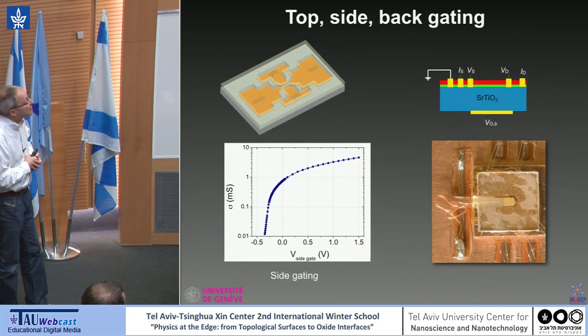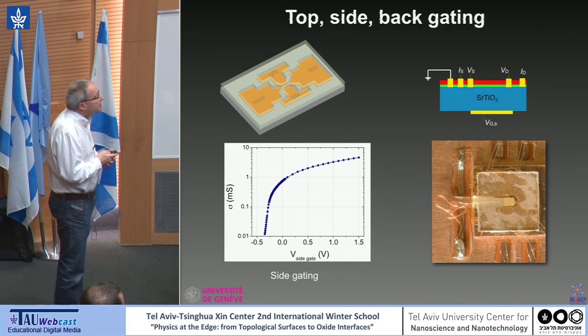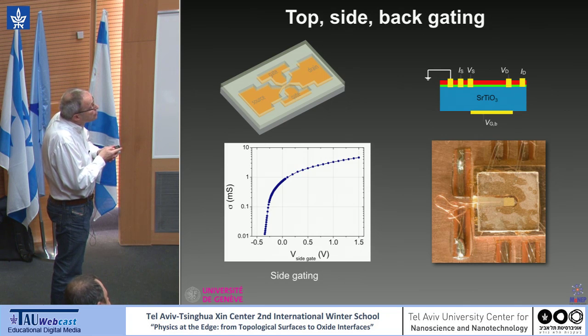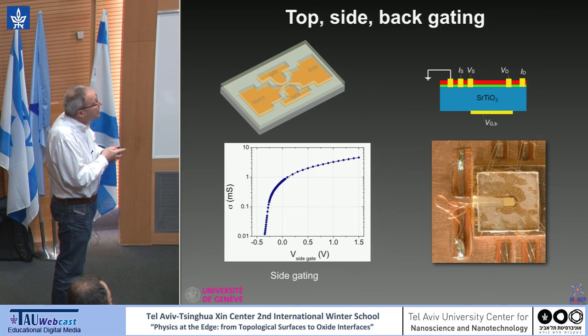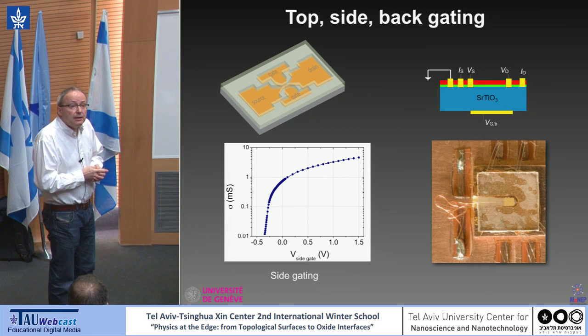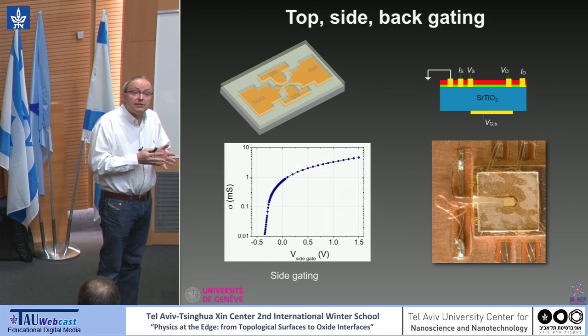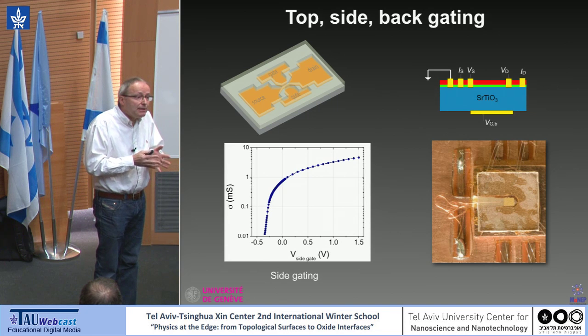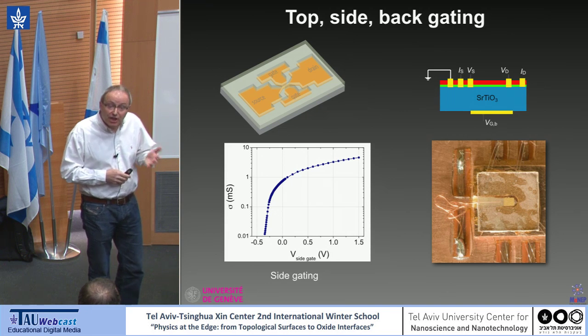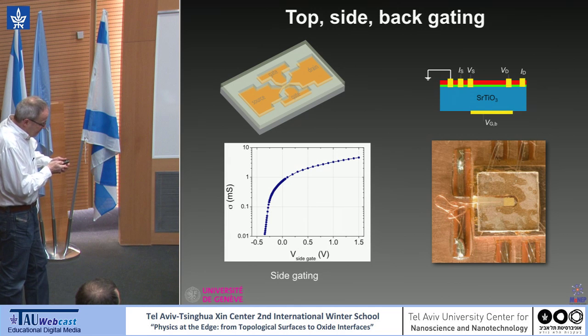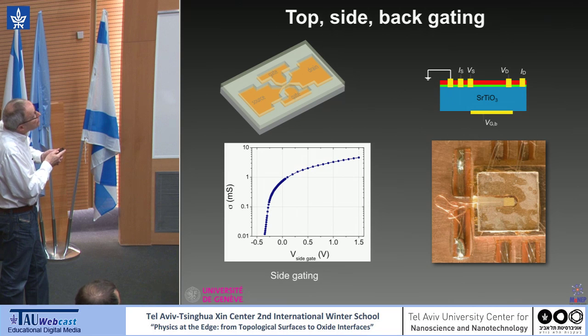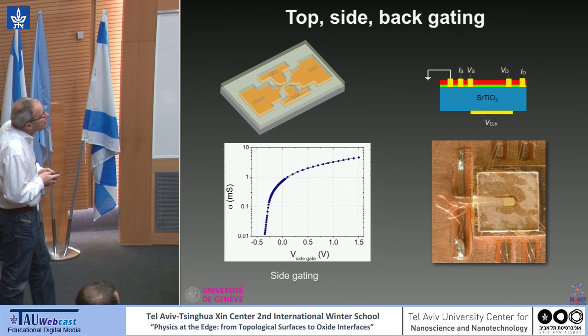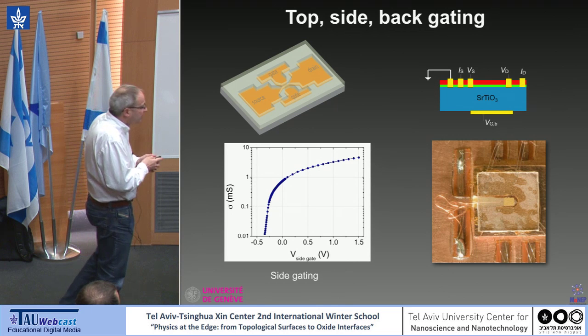And this is indeed what we did. Many groups have been exploring field effect with this system. You can use your strontium titanate crystal as a gate dielectric, so you put a gate on the back side. The strontium titanate crystal is thick, typically 0.5 millimeter, which means you will have to put quite a large gate, but it's in fact quite convenient. You can also put your gate on top of lanthanum aluminate, or you can even use side gates like here. And this is a side gate experiment where we see the change in conductance as a function of a few volts, and you see the very large effect.